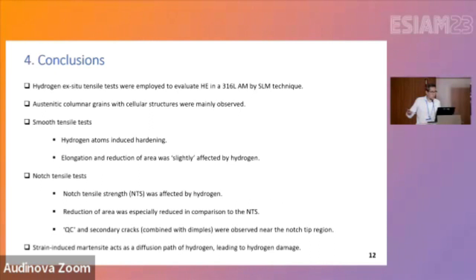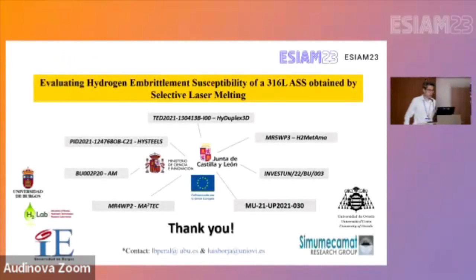Although this work is ongoing and we need to conduct more trials, here we present some conclusions. Regarding the smooth tensile samples, hydrogen atoms seem to induce hardening, and ductility was slightly affected. However, in the case of the notch tensile specimens, the notch tensile strength was affected by hydrogen, and the reduction of area was especially reduced in comparison to the notch tensile strength, which can be explained according to the fracture micromechanisms observed in the fracture surfaces. It is also important to say that martensite acts as a diffusion path for hydrogen, giving rise to hydrogen embrittlement phenomena. So thank you very much for your attention.